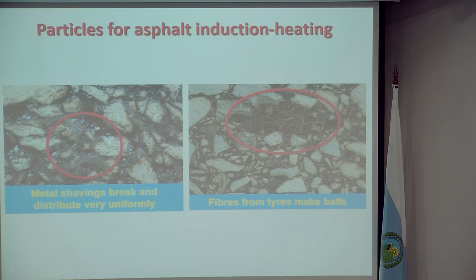Obviously, there's potential for that to be heated, and it may be beneficial, but in terms of spreading that actual effect throughout the asphalt mixture, that's probably not what you were looking for in terms of that bulking up. So the study that we've looked at, or the research that's been done over the last 2 years, has really concentrated on using steel wool, which is quite easy to distribute within an asphalt mixture. We can actually produce specimens.